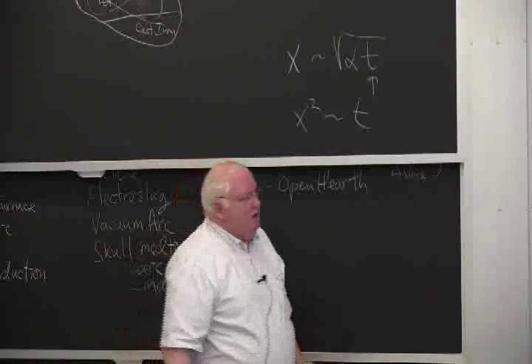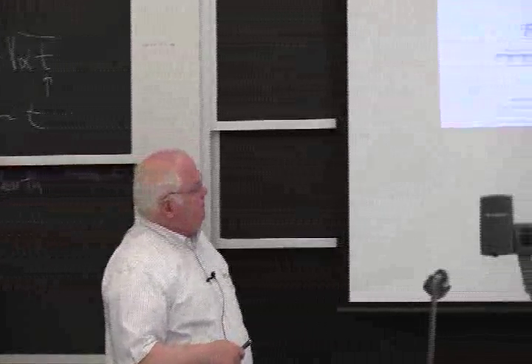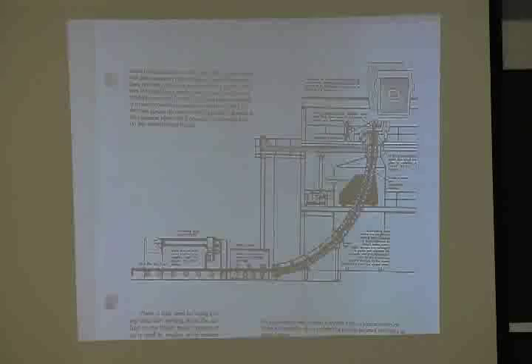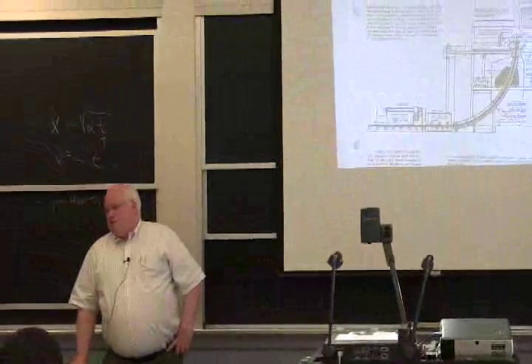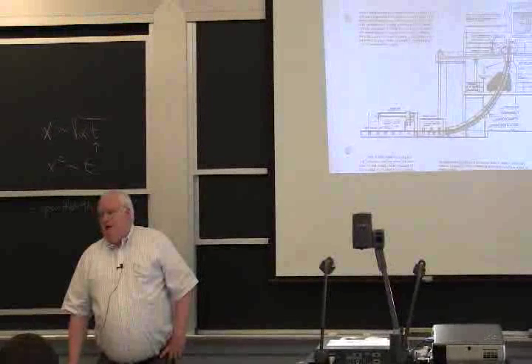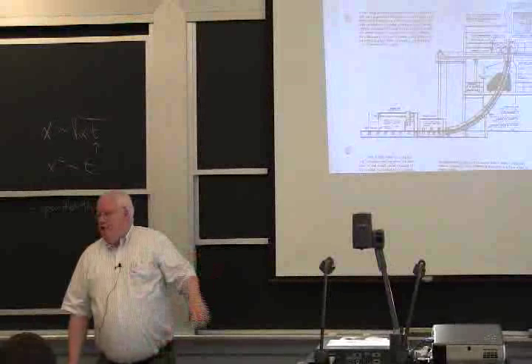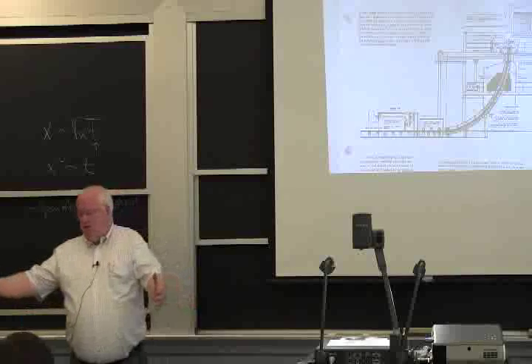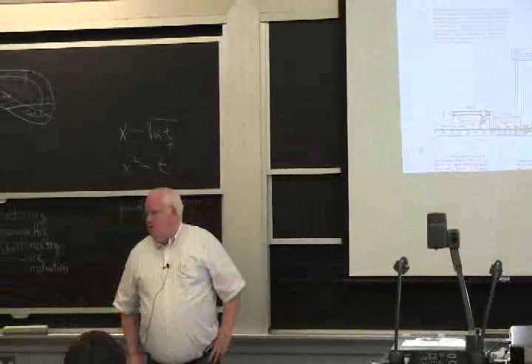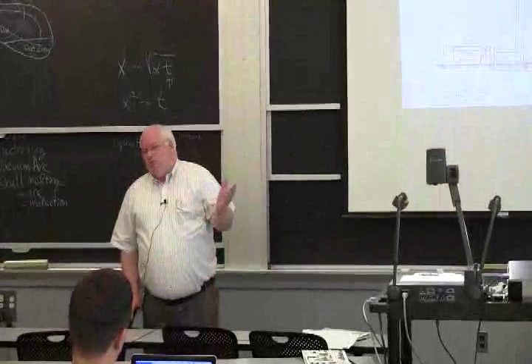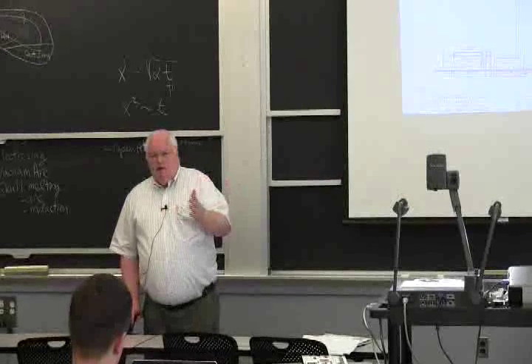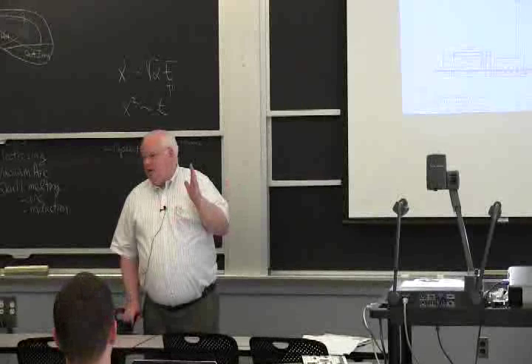So about the thickest we can go is something on the order of 10 to 12 inches. You'll have some defects in here, you're going to have to roll it to get rid of some of those defects. So generally the thickest plate we would make by this is 2 to 4 inches thick, okay? Anything thicker than that, we still have to go back to the old-fashioned ingot casting. And ingot cast molds can be 30, 40 inches thick, okay? Typically, the old ingot casting lines, you have 300 tons of steel, you might cast 15 ingots. So it's about 20 tons an ingot.